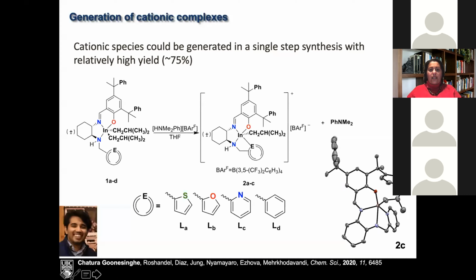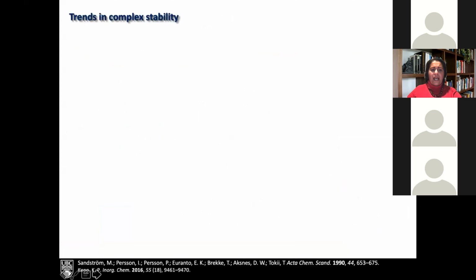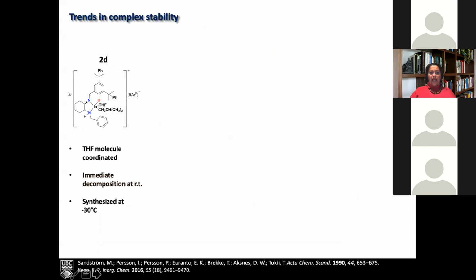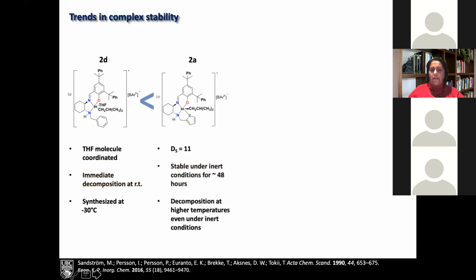So what he was able to do was form these dialkyl complexes, with an amine, imine, and a phenoxy ligand with this arm that could potentially come off and on. He generated cationic species by just adding a proton source, anilinium BArF, to this dialkyl compound, generating these cationic complexes. And what he was able to show was that, as expected, the stability of the compounds very much depends on the donor. So when he didn't have a donor, these were very unstable complexes. They would immediately decompose. If we go to a sulfur compound, the stability increased. It still decomposed at high temperatures, but it was stable under inert conditions for about 48 hours.